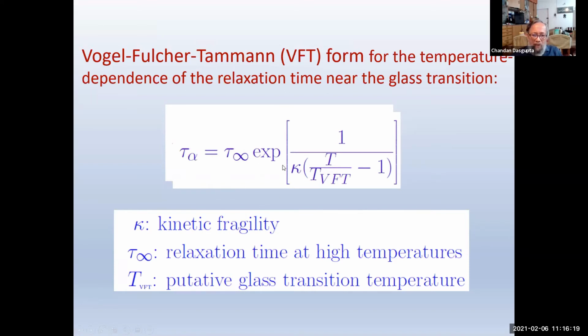And there is a parameter here which I'll refer to later on, this kappa, which tells us about the rate at which this tau alpha grows as you are reducing the temperature. And Austin Angell coined this term fragility. So different glass forming liquids are then classified. Of course, this T_VFT is also going to change as I go from one system to another, but this fragility also changes. And so both of these quantities are of interest. So this is a very brief introduction to the phenomenology of the glass transition.